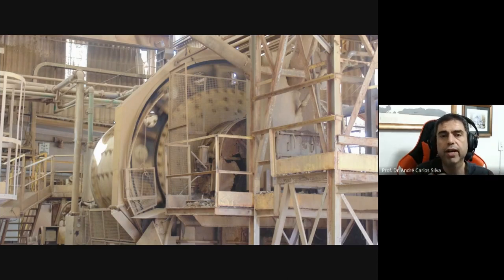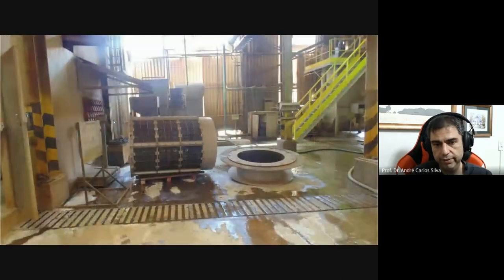It can provide you the right angle, and also the profile of the liner that you use can make this effect more pronounced or even less pronounced. So you choose the liner in a very smart way in order to lower the energy consumption, and on the other hand, have the maximum of the mineral breakage as you want, okay?